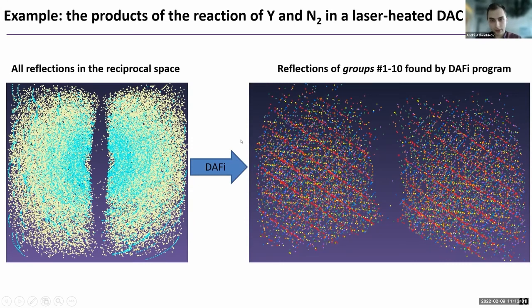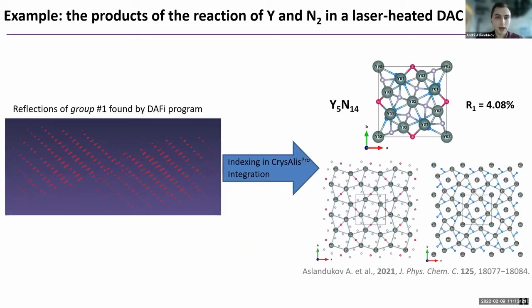And the DAFi program was asked to find 10 reflection groups belonging to distinct single crystal domains, and it took the DAFi program a few minutes. And here you can see all found 10 groups marked by 10 different colors. After indexing and further integration of reflection group, for example, number 1, the crystal structure of the reaction product yttrium 5 nitrogen 14 can be solved and refined down to around 4%.